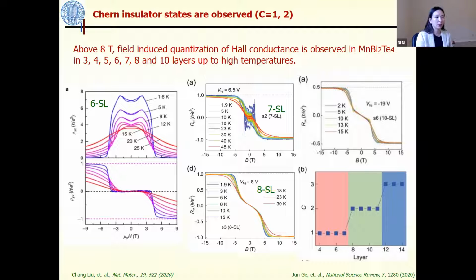Can we make intrinsic antiferromagnetic topological insulators with smaller saturation field? If we make a smaller saturation field, then the field-induced quantized Hall effect can be observed at lower field rather than 8 Tesla, right? Or even sweeter, can we make intrinsic ferromagnetic topological insulators so that the QAH effect can be realized at zero field and high temperature?